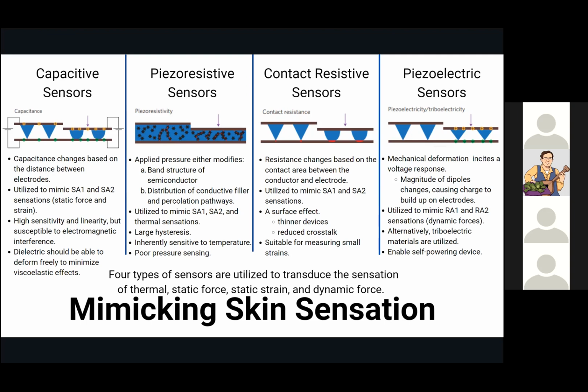The second mechanism utilized by contact resistive sensors is due to a change in geometry. So when a pressure is applied, the device is stretched, increasing length and decreasing contact area. And both of these, both piezo-resistive sensors and contact resistive sensors, when that stress is applied, will result in an increase in resistance, which is again transduced by methods we'll look at in the following slide.